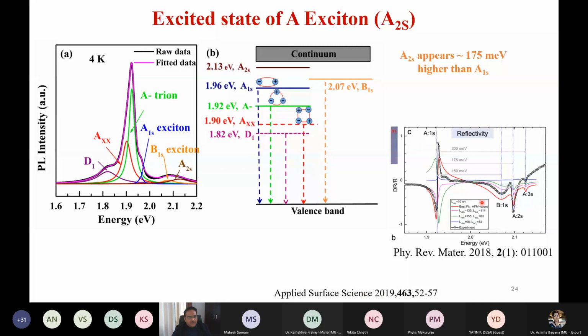Now, based on the 4K data, we have proposed the energy level diagram. This is the valence band and this is the continuum, like the conduction band here. Now the various transitions, we tried to map them. This is 1.8 eV, which is D1, the sulfur vacancy defect bound excitons. We have 1.90, which comes from the bi-excitons, and then you have the A minus trion, the first excited state of the A exciton, and the second excited state of the A exciton here. And here you see the B exciton.